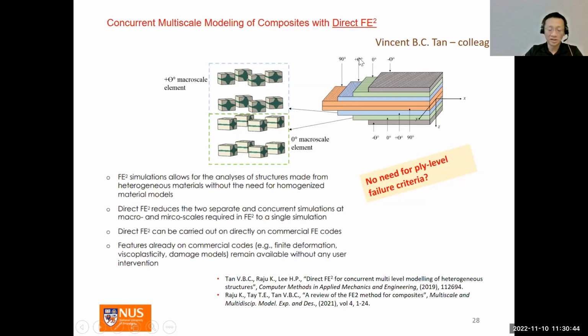Very briefly, by replacing the homogenized material properties of a macro finite element with RVEs of the fiber matrix composite at the Gauss point, we can perform the multi-scale analysis in a single step, single model. So for example, here we have two adjacent plies. The blue one on top is oriented at an angle plus theta, and the green one at the bottom here is oriented at 0 degrees, let's say. And let's say they are modeled by 3D finite element brick elements. And so for each of these elements, you would have 8 Gauss points.